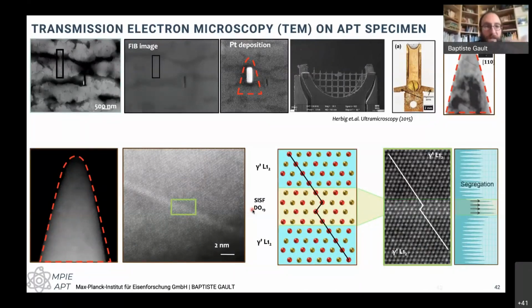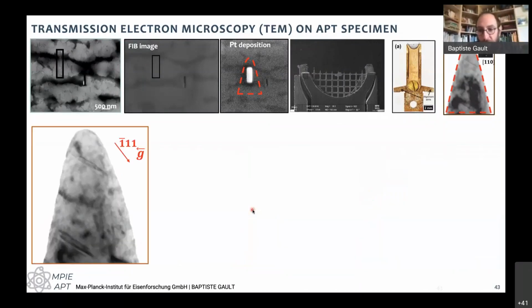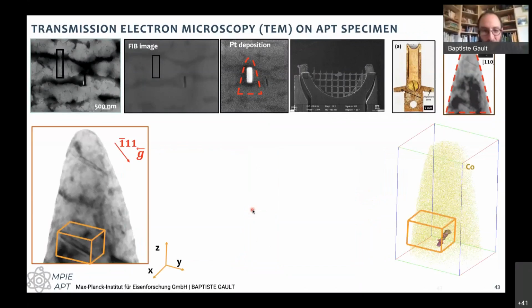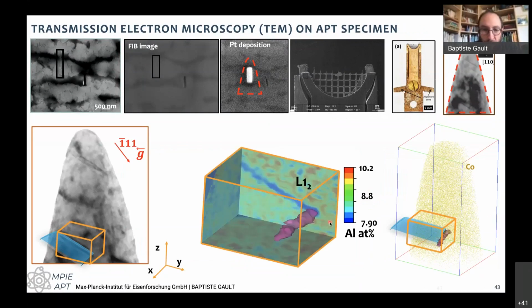And then we stuck this sample into the atom probe, and it took us quite a long time to actually find out that the stacking fault was inside the data. But when we looked at it, we zoomed onto this region, and what we found was a tubular region that was really high in chromium, and that actually corresponds to the leading partial dislocation that has crossed into gamma prime. And in the wake of that dislocation, we can see here, for example, a region that is depleted in aluminium. And because of the high resolution STEM that we had done before, we knew that it was most likely segregated by something heavy. In this case, it would be some tungsten.